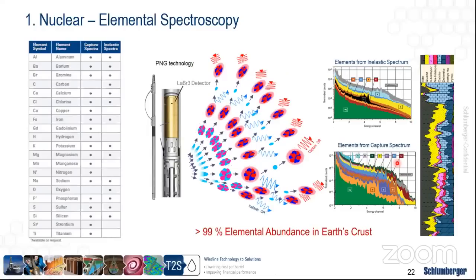The capture spectrum is a bit different, where we basically emit neutrons, and then due to this interaction, they lose energy, and due to this lost energy, they start to be absorbed and captured by the elements. And then the capture elements start to emit a signature gamma ray that is collected back by the tool. By analyzing the two different types of spectrums, the inelastic spectrum and the capture spectrum, we're able to measure more than 21 or 22 elements that are present in the Earth's crust, and this can solve more than 99% of the elements present in the Earth's crust.